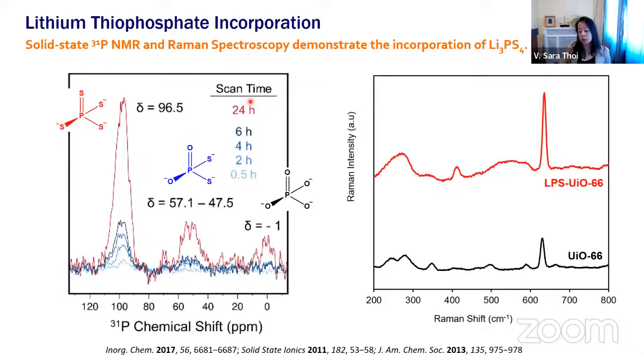We also could use Raman spectroscopy to show that we have a very robust signature of 412 wave numbers indicating this PS4 vibration. And then if we look at the zirconium oxygen bonds in this cluster, we actually see some profile changes, which gives us a clue that this thiophosphate is very likely bound to that zirconium cluster, thereby changing the Zr-O bonds within the zirconium cluster.